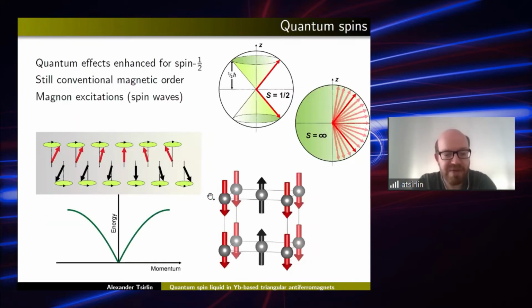For this, we again have a very direct recipe from the theoretical physics. It tells us that as we reduce the size of the spin, then it becomes more and more quantum, right? Because if I take spin 1/2, it can have only two projections on the quantization axis. So there is clearly a very strong quantization effect. But if I go to the large spin, eventually to the infinite spin, then any projection is possible, and then the large spins behave classically. So I definitely need the low spin.